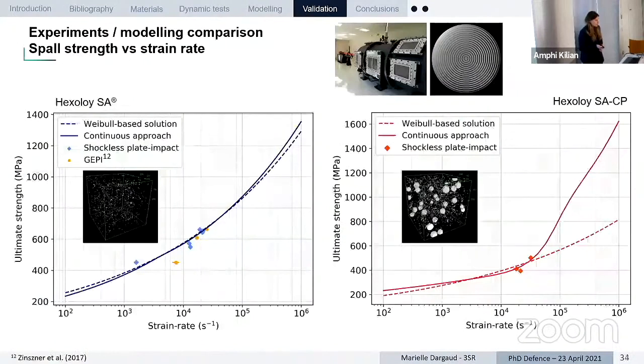Now, when we compare the results of the shockless plate impact with the prediction, we can see that for both materials, we have an extremely good prediction with the DFH model. We can see that we have a good fit with the experimental data, and still here we know that we would need to perform some more experiments at higher strain rate to be able to demonstrate experimentally that using flaw distribution based on tomography data, capturing the smallest flaws, would be required to have a proper description of the material.